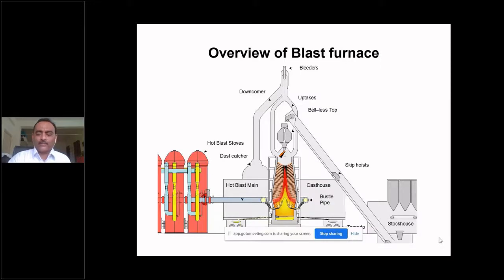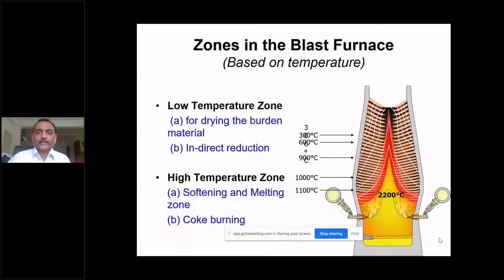So this is the basic thing in the blast furnace, by which the blast furnace runs. These are the temperature zones. In front of the tuyere, this is called the tuyere, from where the air goes inside. The maximum temperature is near about 2200 degrees centigrade. Everything which is charged inside the furnace except coke is melted, while coke is burnt. From top to bottom, the temperature will increase.